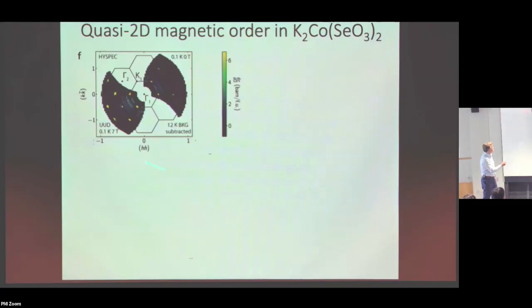And this was actually a surprise to us as we did the experiment. What I'm showing you here is the wave vector dependence. This is the triangular reciprocal lattice plane, and I'm showing you the intensity of scattering on this kind of false color scale, and I'm showing you data both at 0 Tesla and at finite field.